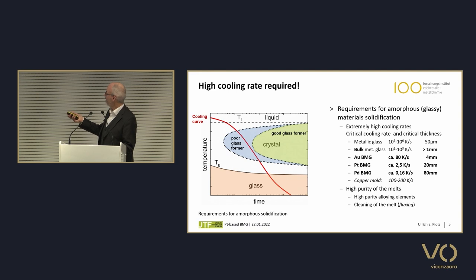Now here are some critical cooling rates, we call this, that are required to form the bulk metallic properties. And we see that for gold-based bulk metallic glasses, we have 80 Kelvin per second, for platinum, 2.5 Kelvin per second, and for palladium, we have only 0.16 Kelvin per second, which is quite slow cooling, and therefore we can reach really high thicknesses in these palladium bulk metallic glasses. Gold requires quite high cooling rate, palladium quite low, and platinum is in between.